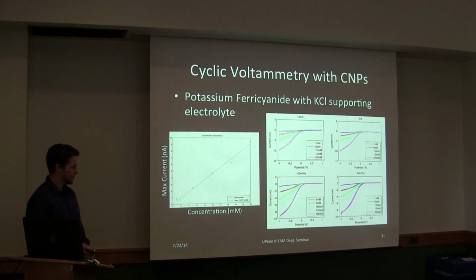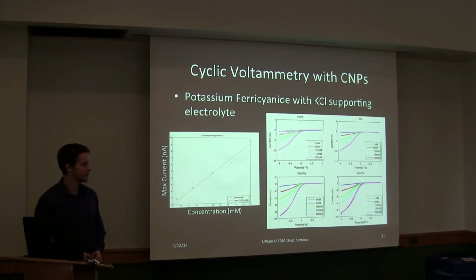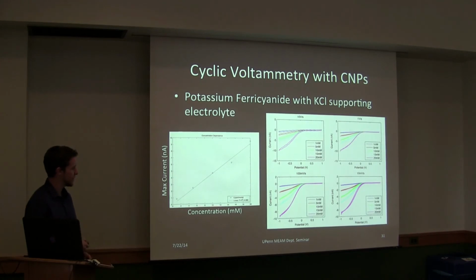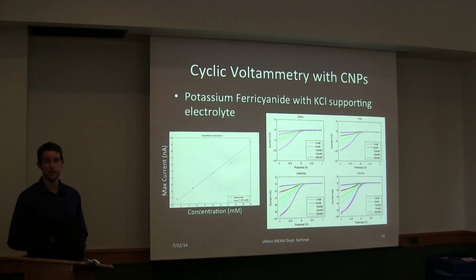So here's just a quick characterization we did looking at cyclic voltammetry with CNPs. These plots are the current versus potential at different scan rates, so going from 10 millivolts per second all the way up to 10 volts per second. And in the microelectrode regime, you typically, under most normal scan rates, get almost a steady state current response. So there's not a huge difference in any of these curves. And we do recover a classic sigmoidal shape, which is characteristic of microelectrode cyclic voltammetry. And we can also look at the maximum current versus concentration. And typically the current in CV is proportional to concentration.